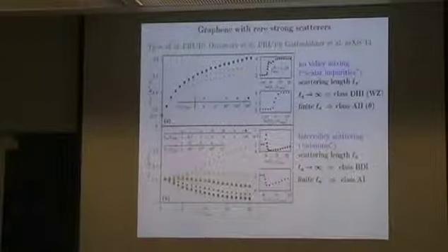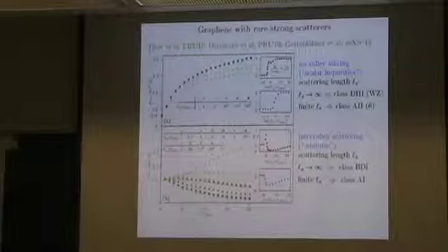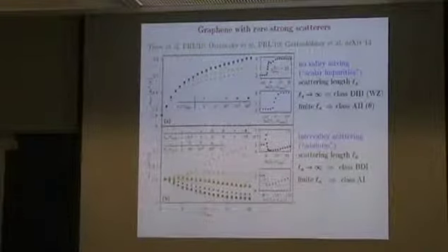So how you propagate between the scatterers, you know the scattering matrix of each scatterer. However, the positions of scatterers are random, and so you get a random matrix, but it's of the size not of the lattice, but rather of the number of scatterers. Yeah, that's what we call unfolded scattering theory. But anyway, this is then put on a computer. And this is a very efficient way to do it numerically for this type of scatterers, which are really rare and isolated.